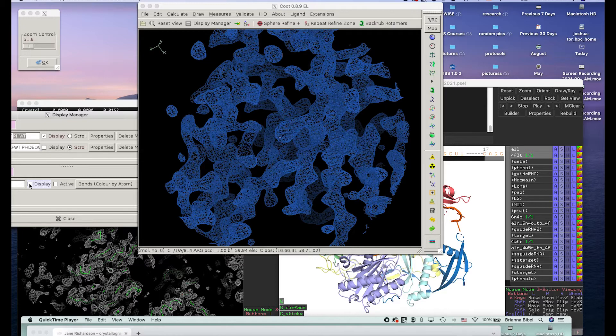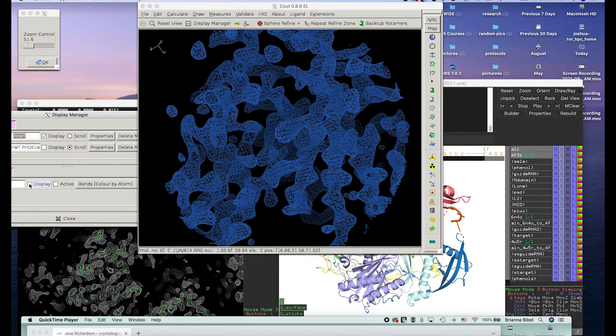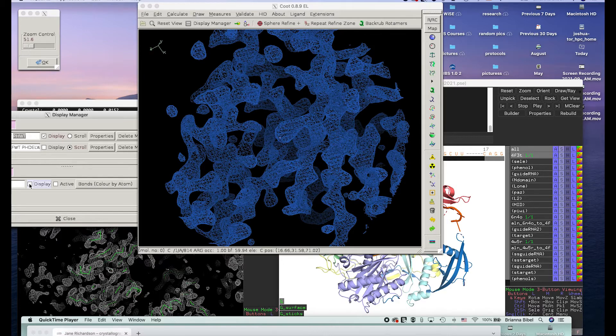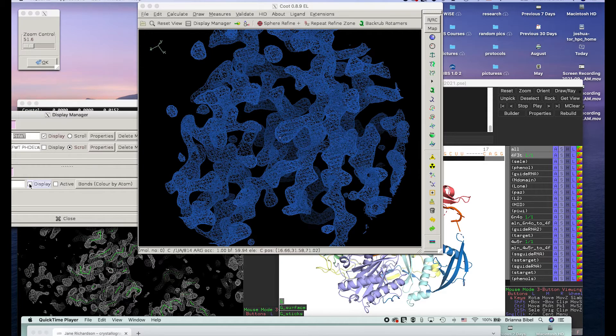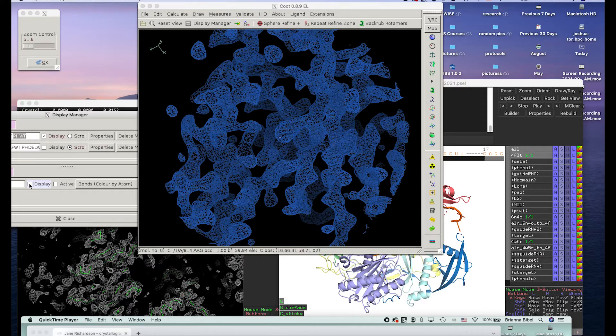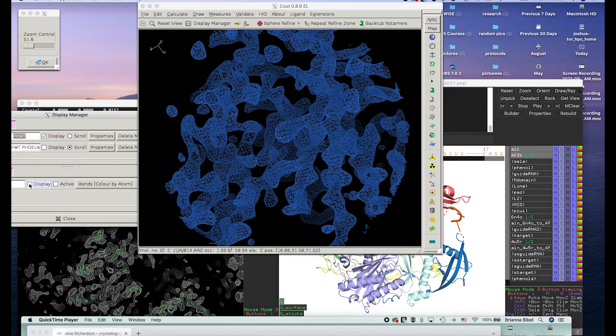Because we need, we're going from the spots, we do that Fourier transform to get to that electron density map. And so remember, the electron density map is this thing, this meshy thing. And so in order to get a map like this, we actually need to figure out those phases. And so there's different methods you can use to initially kind of guess the phases. So there are things like molecular replacement, where you can take a similar protein. So maybe you have a related protein, a really similar related protein. You want about at least 40% or so identity.